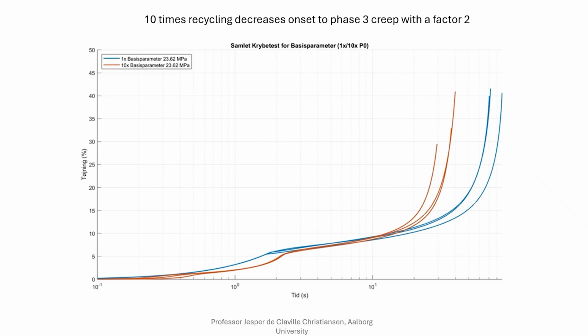And the scale bar is logarithmic on the time axis, which means that you have onset to phase 3 creep, where you start to get damage in the material, almost a factor 2 in difference between the recycled and the virgin polypropylene. So for creep behavior, creep loaded samples, it is important to acknowledge that recycled material do not have the same mechanical properties.